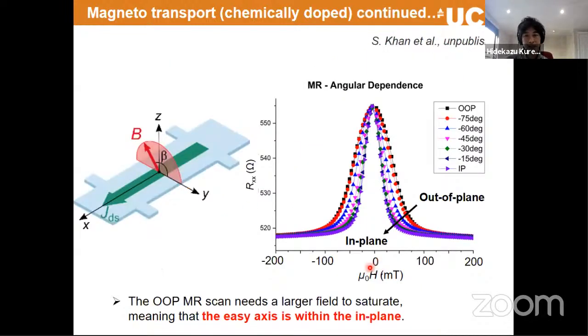And also the key measurement here is that this peak behavior is slightly different in terms of the shape when we apply the magnetic field out of plane. When we apply it out of plane, this width is larger, compared to when we measure in plane, where the width is narrower. So if this is coming from the magnetic anisotropy, what we can tell you is that it requires a larger magnetic field to fully polarize your local magnetic moment along the magnetic field direction compared to in plane.